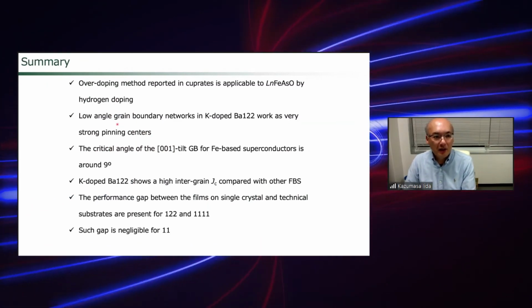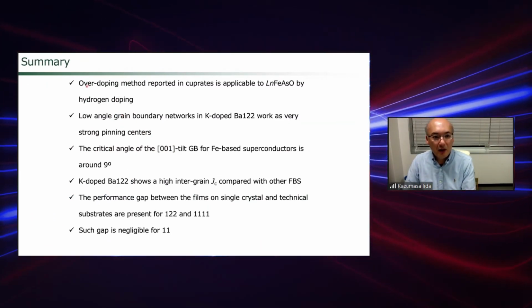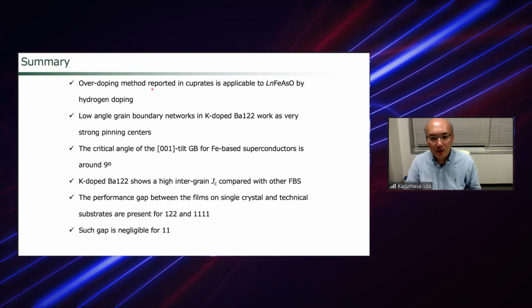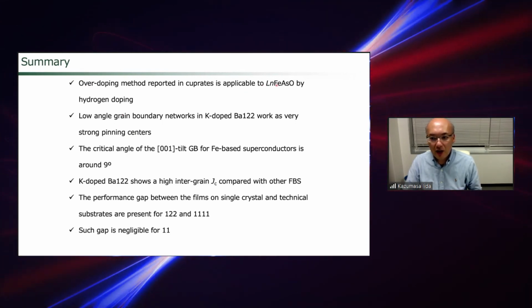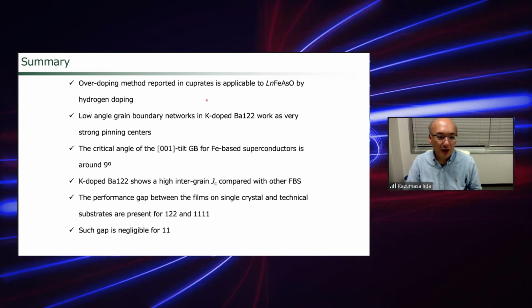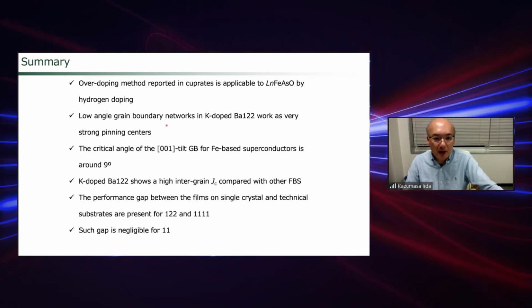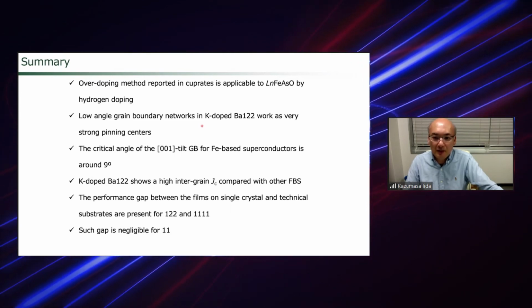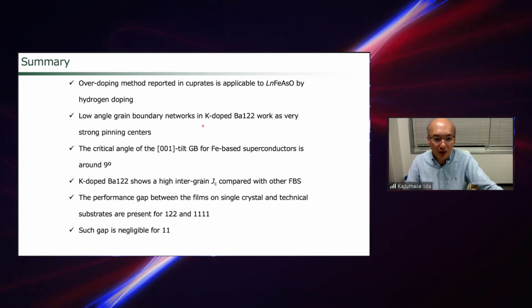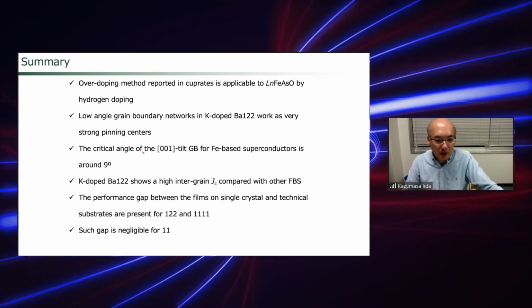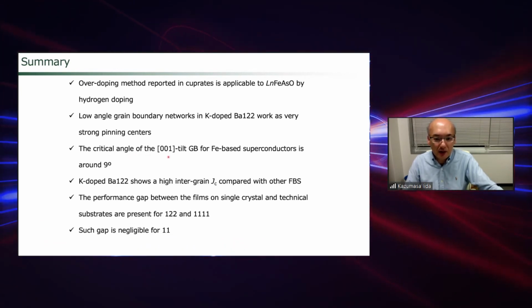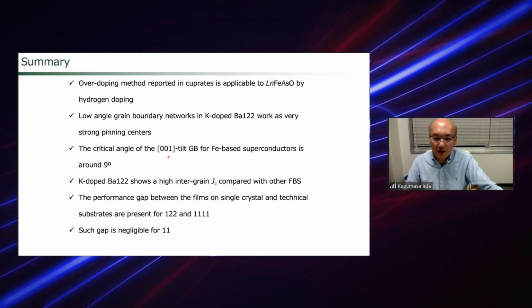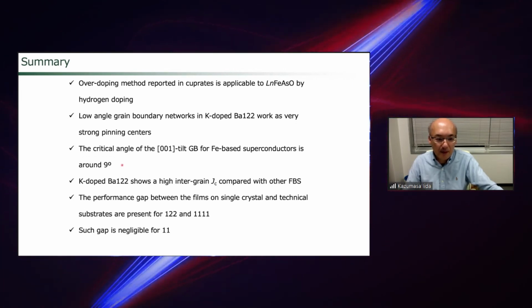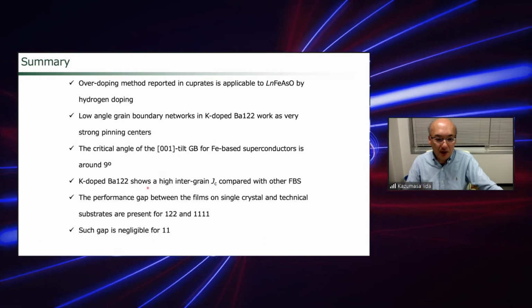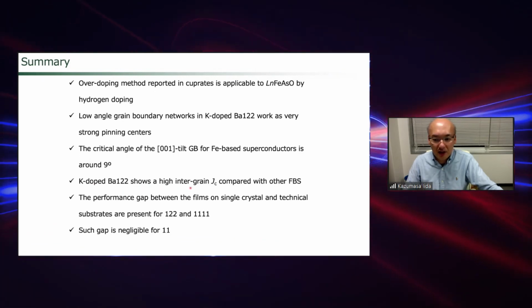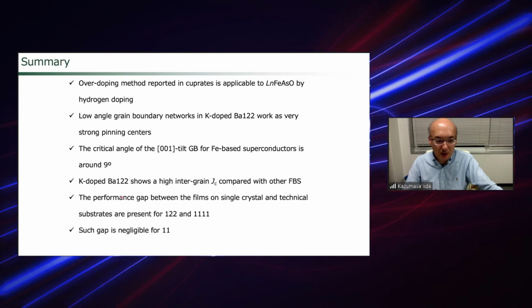Okay, let me summarize my talk. The overdoping method reported in the cuprates is applicable to lanthanide iron arsenic oxide by hydrogen doping. Low-angle grain boundary networks in potassium-doped barium 122 work as very strong pinning centers. The critical angle of the [001] tilt grain boundaries for the iron-based superconductors is around 9 degrees. Potassium-doped barium 122 shows a high intergrain Jc compared with the other iron-based superconductors.